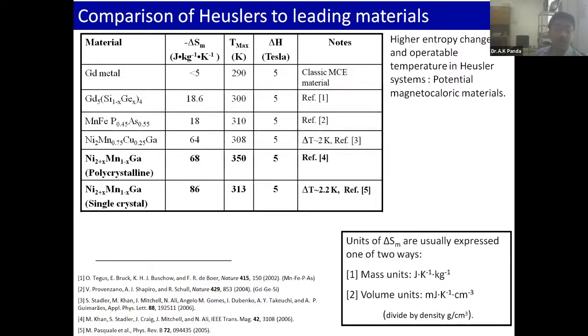But when you modify it with silicon germanium, you can raise the entropy to 18.6 at a peak around 300 Kelvin, which is more or less the same as in the case of gadolinium. But you can make out that the entropy rises more than 3 times. And that is where the first order phase transformation works. That is due to the martensitic structural transformations. And of course, the equivalent is manganese iron phosphorus arsenide. Arsenic is there. Certainly, none of you would appreciate it because you do not want arsenic in your material. It is poisonous, despite its very interesting properties.